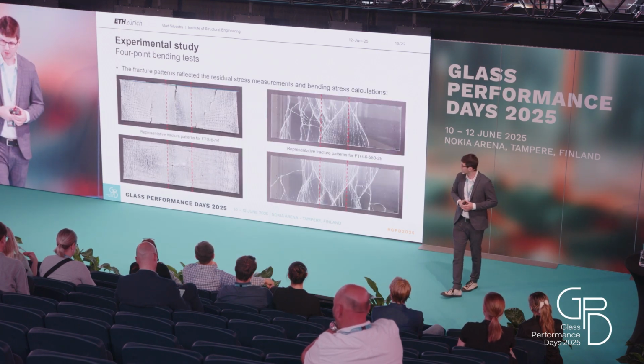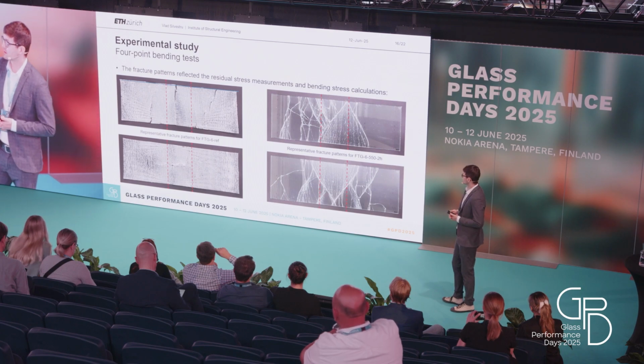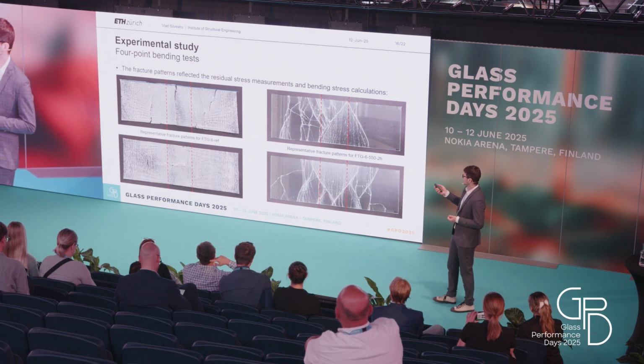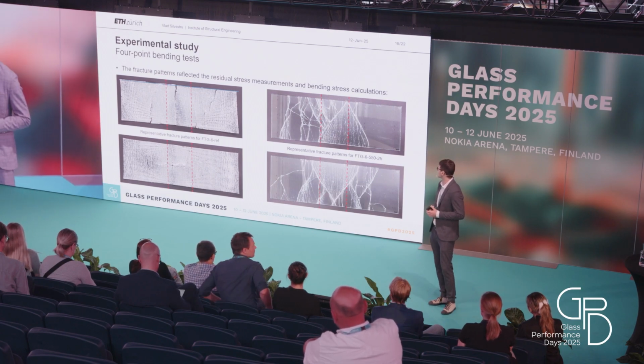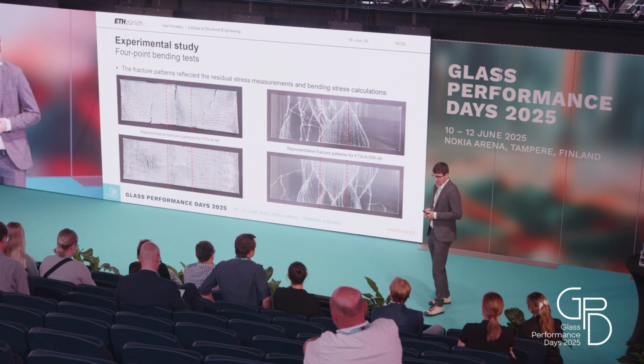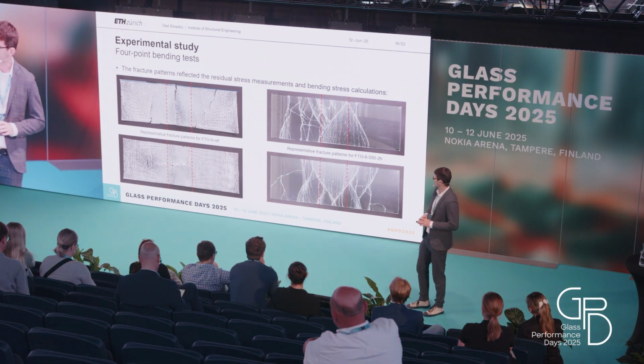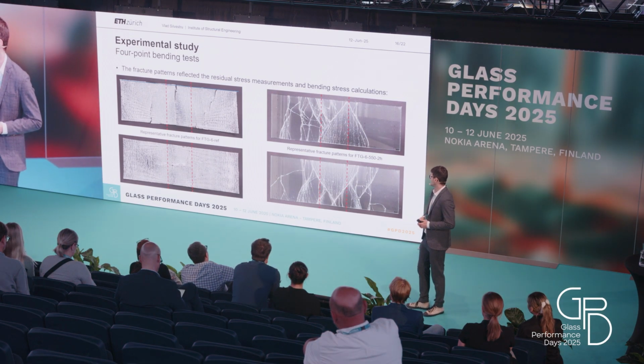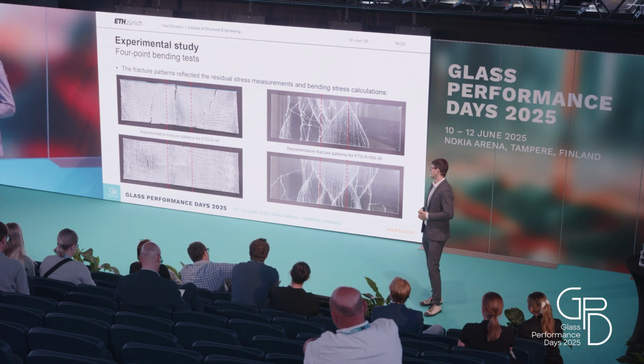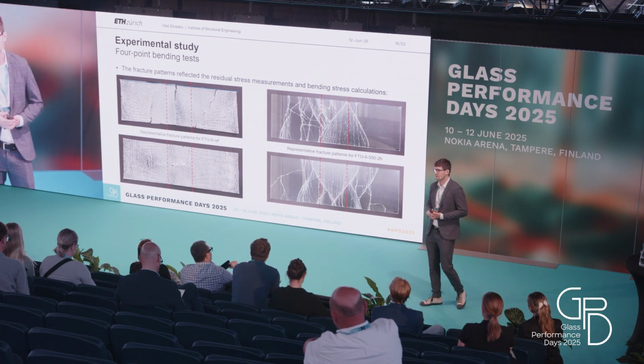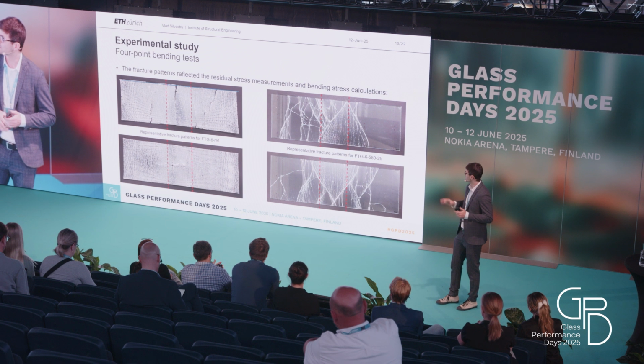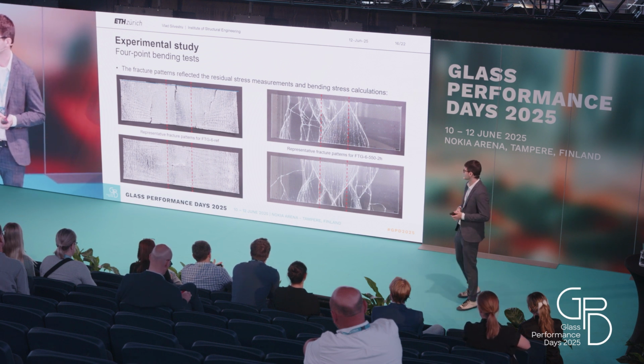I would like to focus a bit more on the fracture patterns. So we can see here on the left side two representative fracture patterns from the fully tempered glass, the reference series. You can see that the fragments are very small, so the degree of tempering was quite high for these glasses. Also, the failure during the test was quite explosive.